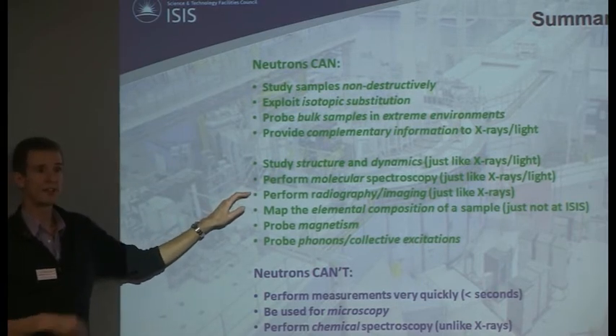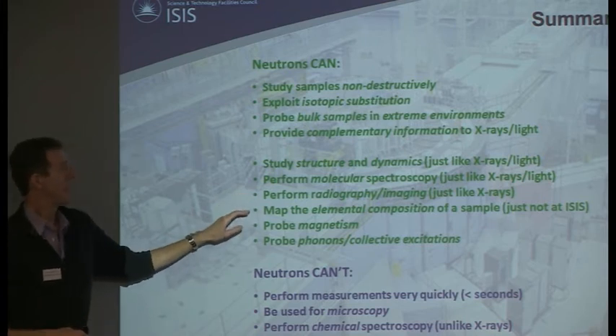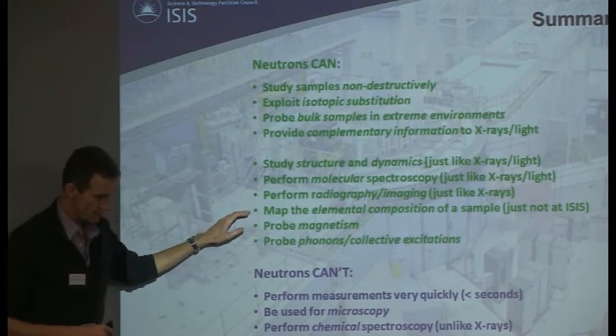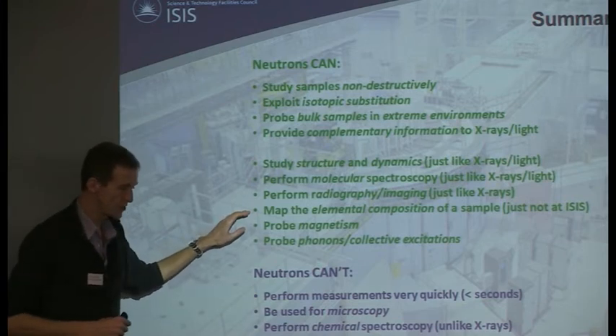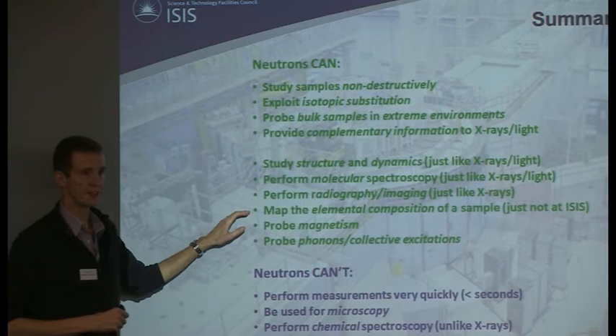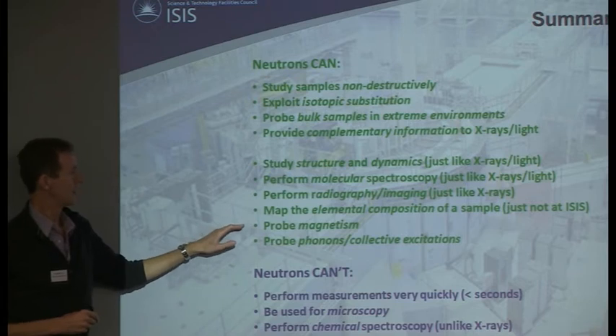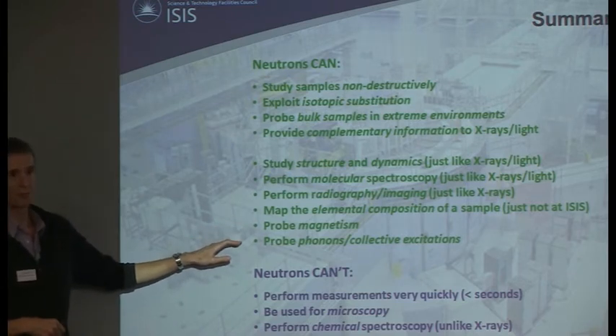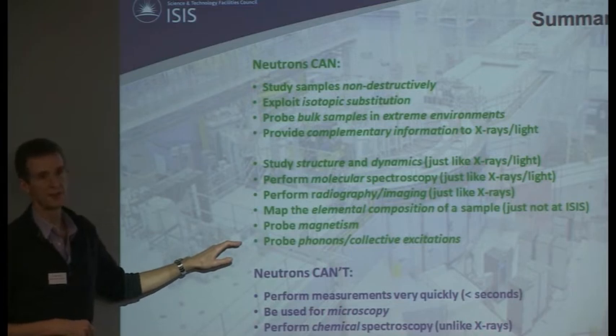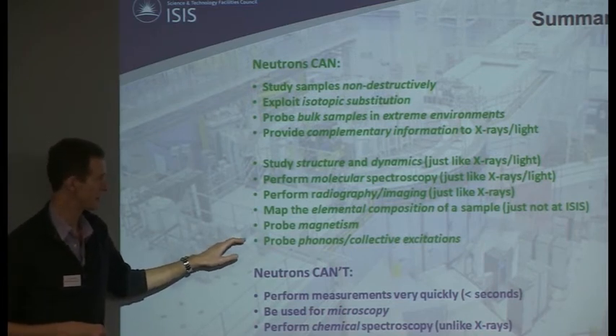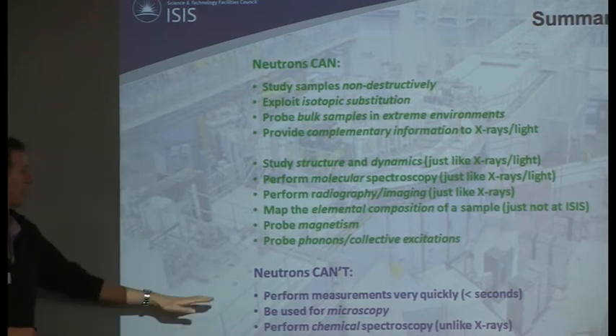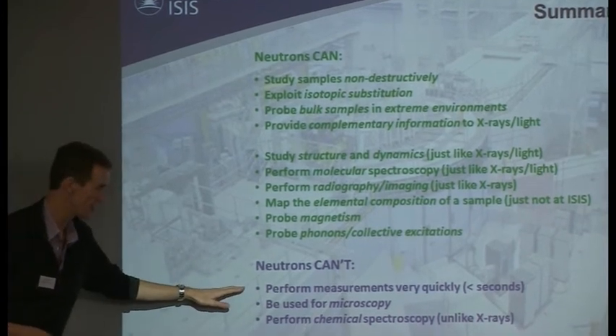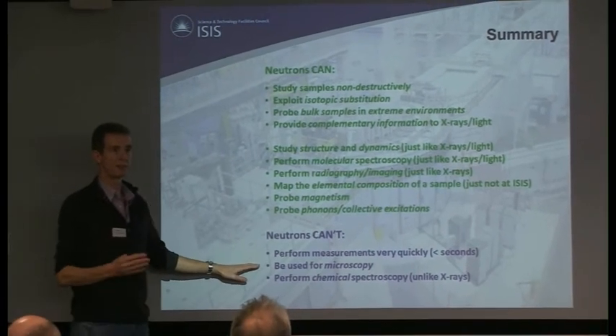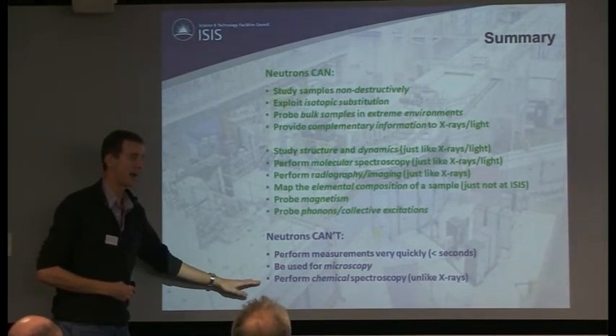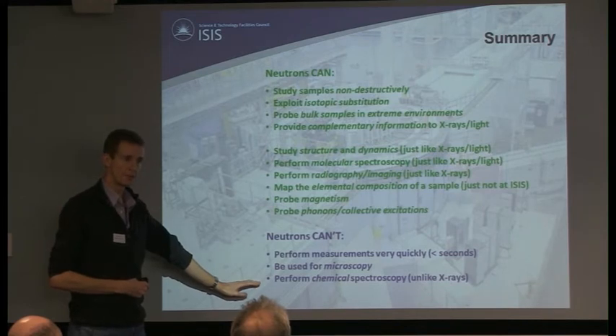We can do radiography and imaging, as Winfried is about to tell you. It is possible to get some chemical elemental composition data out with neutrons, though we can't do it at ISIS at the moment, unless Winfried corrects me. They're a good probe of magnetism, and you can probe the thermal and conductivity properties of materials in spectroscopy. What we can't do is really high time resolution experiments, microscopy of the type that Fred was talking about, or chemical spectroscopy. Those are the differences.